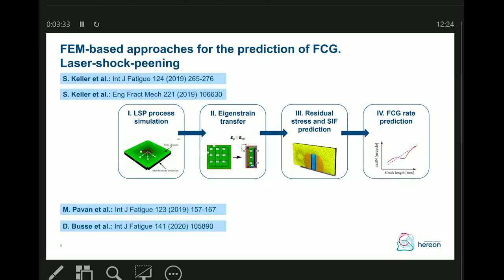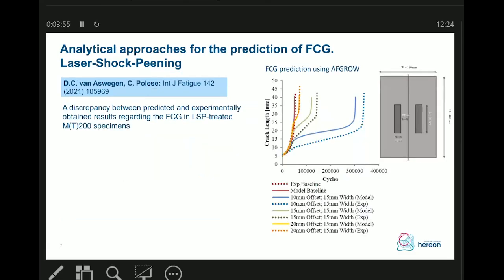However, we first have to perform laser peening process simulation, for example using the Johnson-Cook model. Then we can introduce residual stresses in the finite element model, then a similar fracture mechanical analysis and prediction of fatigue growth. There are some papers where this approach was successfully implemented. However, engineers working for the aeronautical industry are interested in using commercial software such as AFGROW or NASGRO, where analytical approaches are implemented for including the effect of residual stresses.